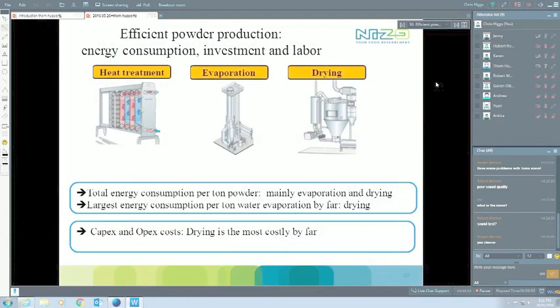Of course, the other thing, if we start looking at running our dryers as effectively as possible, is looking at where I can make savings. If we look at what is taking energy in our milk powder production, of course it's the heat treatment, it's evaporation, and it's drying. But if we look at total energy consumption, drying is by far the most energy consuming. So if we can reduce energy consumed there, and make sure that our dryer is running as efficiently as possible, then we can make quite some savings.